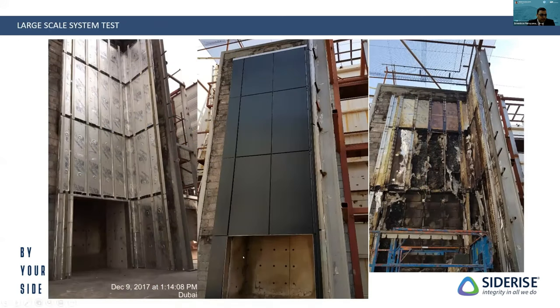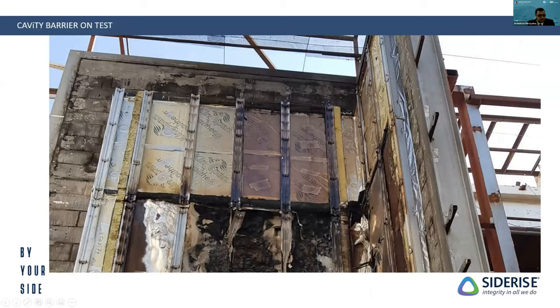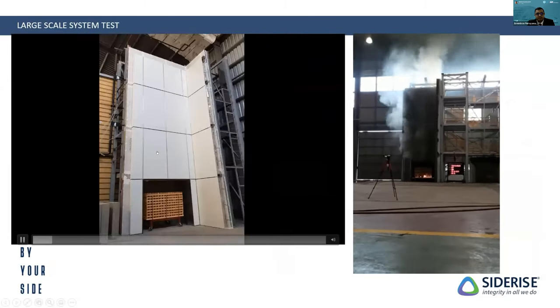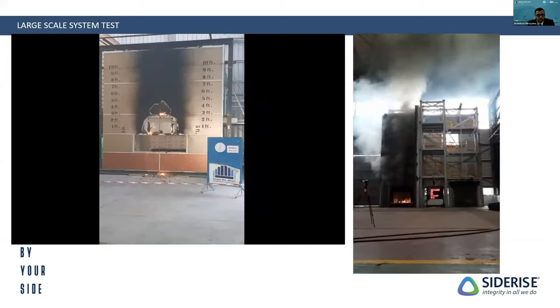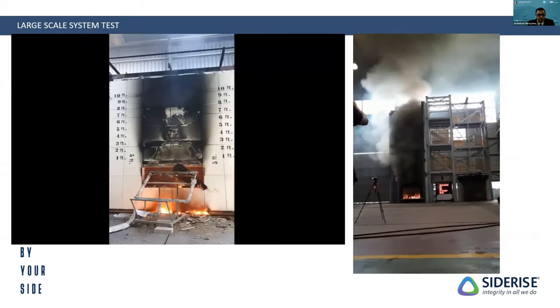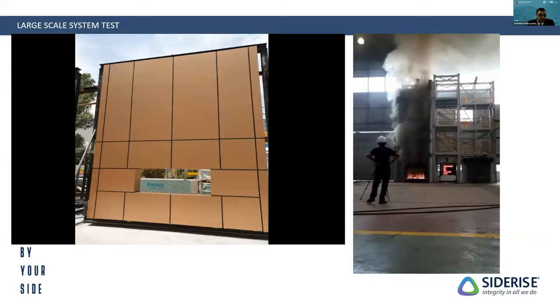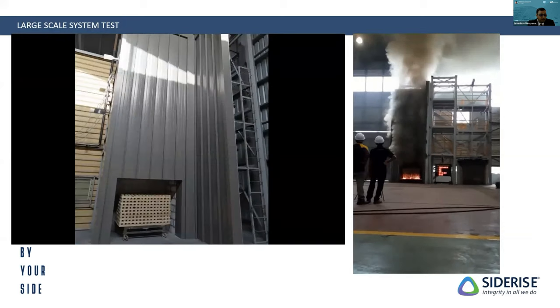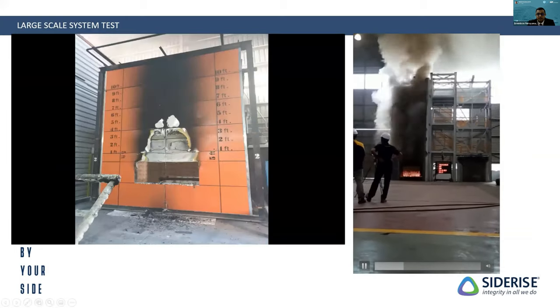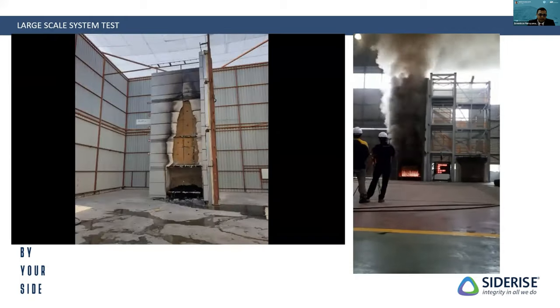An image from our laboratory from testing done in 2017 shows the installation with phenolic thermal insulation, cavity barriers installed, and cladding on top. Once the test is complete and the panels are removed, you can see the intumescent expanded, the reaction of the insulation below and above the cavity barriers, and how the vertically installed cavity barrier has protected the insulation on the other side. At SideRise, we have tested around 250 different systems — different manufacturers, combinations of materials, void sizes, material types, and countries of manufacture.